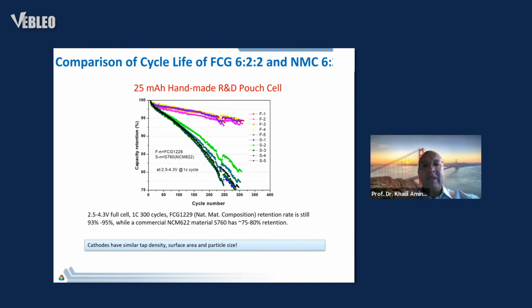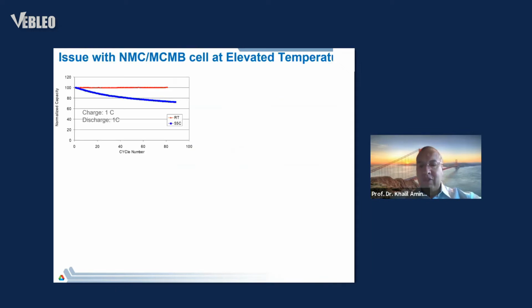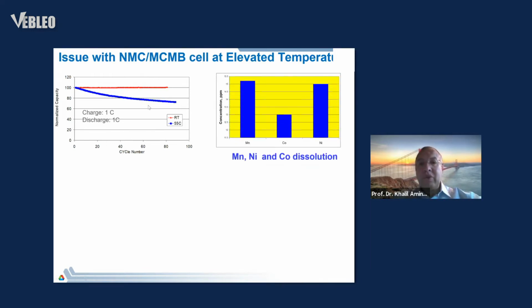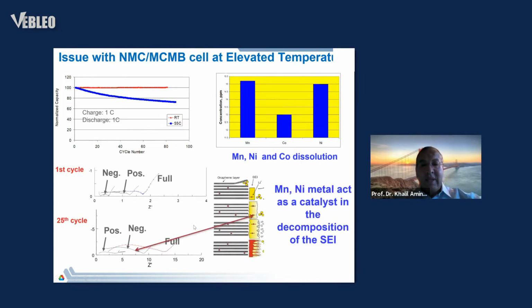We did some pouch cell tests, different pouch cells, to prove that the FCG material outperformed the conventional material. You can see at high voltage, in this case, the cathode is at 4.4 volt. The cell is at 4.3 volt. Now, the problem with the nickel manganese cobalt is as long as you have some HF, you will get some dissolution, and the impact of dissolution, especially if you operate at high temperature, like 55 degrees C, is that the capacity goes down because you have dissolution, as I mentioned, and these metals basically move to the anode side and react to compromise the SEI of the anode. And as a result, you see the interfacial impedance of the anode increase.